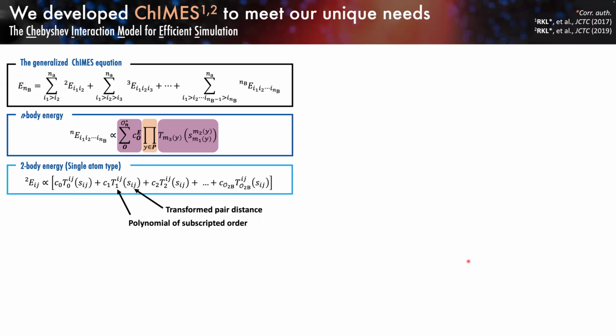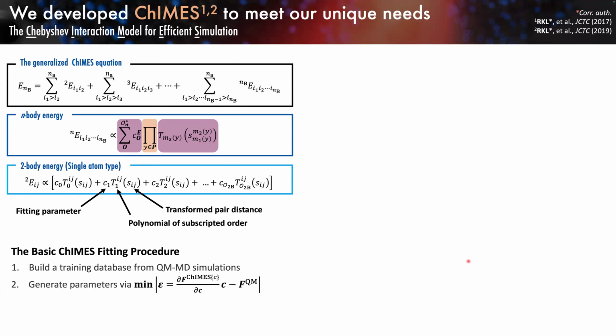The argument S is a transformation of the distance between a given pair of atoms, and the coefficients out front are what we fit when we talk about fitting these machine learning potentials. And so what do we train these things to? What we're going to do is run short first principles molecular dynamics simulations or calculations that give us data that look like coordinates for a system with the per atom forces, an overall system energy, and a system stress tensor.